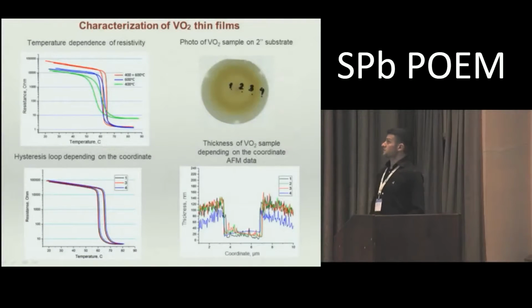Here I show some characterization of vanadium dioxide thin films. On the left picture, you see the temperature dependence of the resistivity of our films. If we skip the second part of our method, we get a wide hysteresis loop of the resistance in the vanadium dioxide thin films. But if we do all the steps, we get a perfect hysteresis curve. After we obtained these good results for vanadium dioxide, we moved to wafer scale samples.